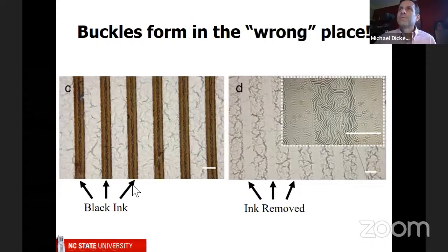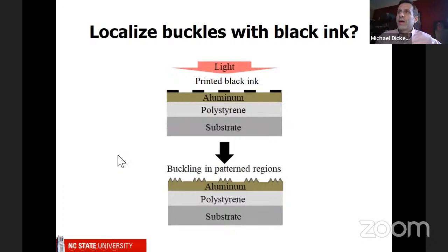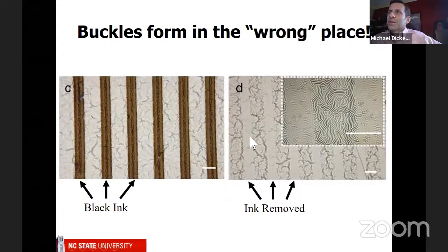So here's our sample, and you can see the black ink. And when we did this experiment, we shined the light on it, and you can see that the wrinkles were forming here. This is the aluminum region. So if I go back, instead of forming here where we thought that they would form, they formed here. And when we remove the black ink, you can see underneath it, there's basically no wrinkles. So this is exciting because it means that we can dictate where these wrinkles go. We can put them here and not here. But it was really confusing because they were not going where we thought they should go.